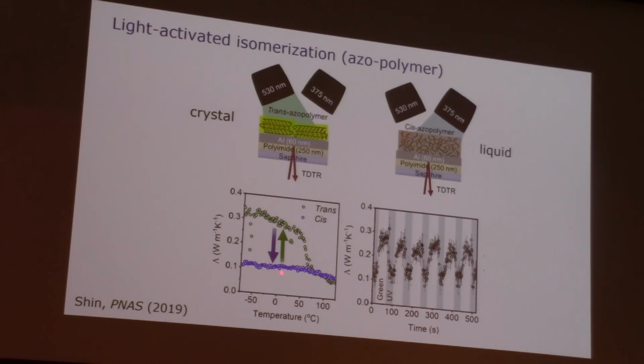And when that happens, the thermal conductivity, this is the cis configuration, this is the trans, at different temperatures. At high temperatures, they're the same because they're both melted. At lower temperatures, you still get a liquid, then a glass. And in the trans state, you get essentially a crystallized material or partially crystallized material. And if you sit at room temperature and go back and forth with light, the thermal conductivity changes by almost a factor of 3. And it does it on a time scale of seconds, tens of seconds, something like that. So here is a light-activated thermal switch.